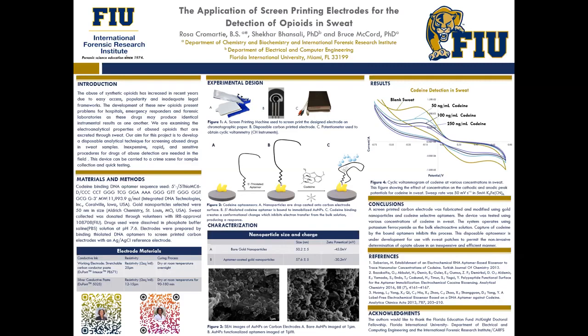So in conclusion, we can see the fabrication and the modification of the screen printed carbon electrode with modifications using gold nanoparticles, as well as the selective aptamers to target for codeine. This test was done using various concentrations in sweat. The system was operated using potassium ferrocyanide as the bulk electroactive solution. And the aptamer that is bound to the gold nanoparticles on the surface of the electrode was used to capture the codeine.